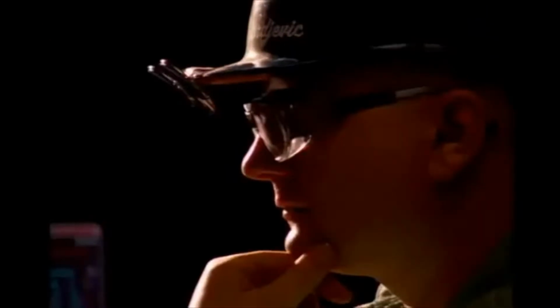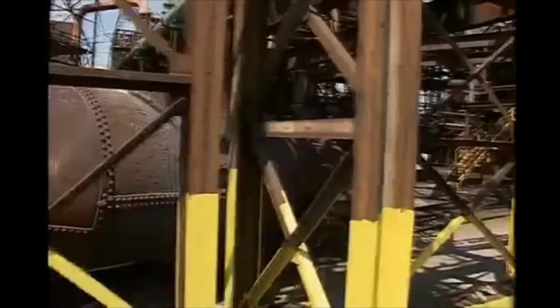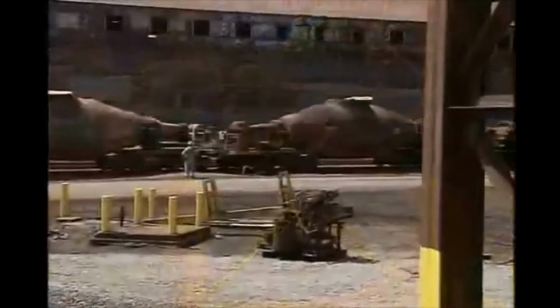From below, a continuous blast of superheated air combusts the coke, intensifying the heat and changing raw materials into molten iron. Sometimes more than 9,000 tons of it a day in our largest blast furnace, where it reaches a temperature of 2,700 degrees Fahrenheit. At regular intervals, we tap this blistering brew into giant submarine ladles that ride on rails to the basic oxygen shop, where iron will be turned into steel. In this fast-paced sequence, up to 250 tons of steel can be made to order in less than 45 minutes.